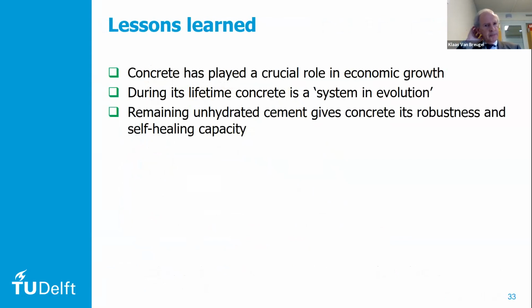Well, we learned from this, looking at all that has been said so far, that concrete has played a crucial role in economic growth. We further have seen that concrete during its lifetime is a system in evolution. It is hydrating, it is cracking, the cracks can heal, or if they cannot heal, there is not enough power to heal them, then you have progressive collapse. And the remaining unhydrated cement gives concrete its robustness and its self-healing capacity.